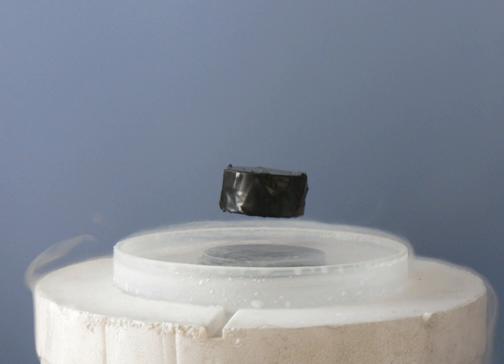Superconductors can be divided into two classes according to how this breakdown occurs. In type 1 superconductors, superconductivity is abruptly destroyed when the strength of the applied field rises above a critical value Hc. Depending on the geometry of the sample, one may obtain an intermediate state consisting of a baroque pattern of regions of normal material carrying a magnetic field mixed with regions of superconducting material containing no field. In type 2 superconductors, raising the applied field past a critical value Hc1 leads to a mixed state also known as the vortex state in which an increasing amount of magnetic flux penetrates the material, but there remains no resistance to the flow of electric current as long as the current is not too large. At a second critical field strength Hc2, superconductivity is destroyed. The mixed state is actually caused by vortices in the electronic superfluid, sometimes called fluxons because the flux carried by these vortices is quantized. Most pure elemental superconductors, except niobium and carbon nanotubes, are type 1, while almost all impure and compound superconductors are type 2.